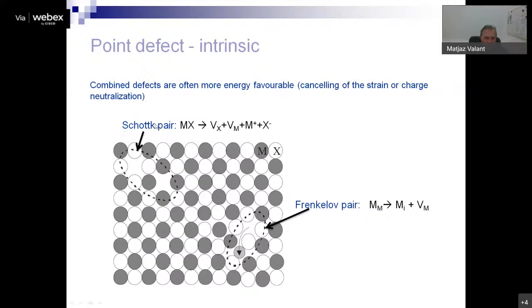I apologize, there should be a Y at the end of this Schottky. Schottky pair, we call this Schottky pair. Schottky pairs in ionic crystals are very common. There's another pair called Frenkel pair. And well, that happens when some particular ion changes its position from a regular site, which is left by a vacancy, into the interstitial site. So we have a vacancy and the interstitial atom. And this again reduces the strain field.